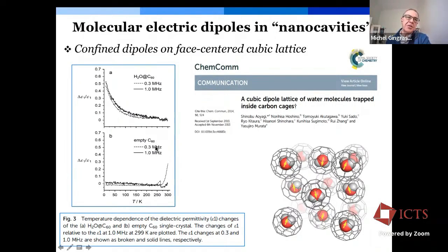So what was measured was the real and imaginary parts of the dielectric permittivity. And what one expects is that if there was a ferroelectric phase transition in such a system, the real part of the dielectric constant would have a singularity at the phase transition. And so these experiments found no evidence for a phase transition for water in C60 down to 8 Kelvin or so. And this is really the first work that launched the interest in exploring the collective behavior of dipoles in the C60.